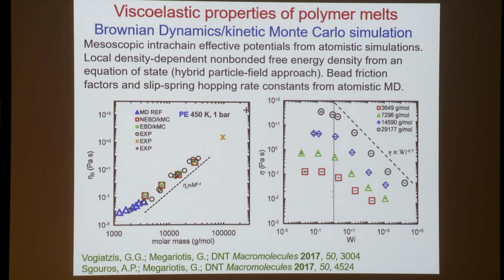So we need an effective potential to parameterize this mesoscopic simulation approach. It is a Brownian Dynamics kinetic Monte Carlo approach. Brownian Dynamics is used to move the segments in three-dimensional space, and the kinetic Monte Carlo is used to introduce these jumps of the slip springs along the chains, and also the creation of new slip springs by the chain ends. For the bonded interactions, we simply invert correlation functions obtained from atomistic simulations to get effective bond stretching and bond bending potentials.